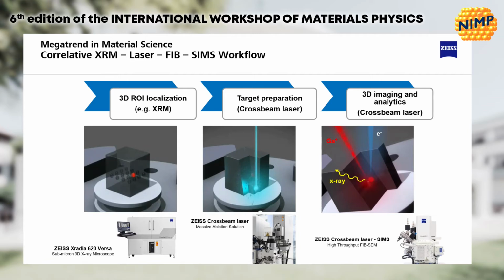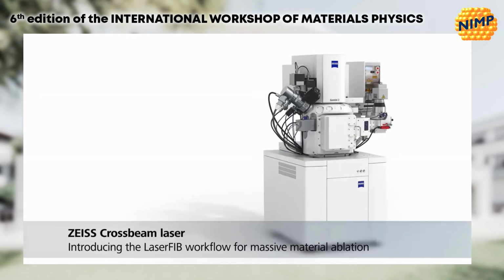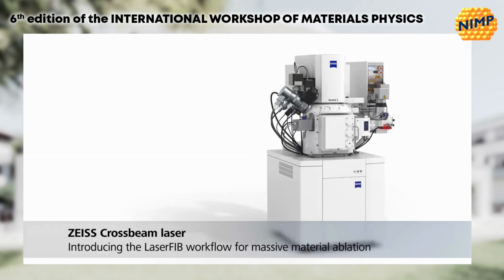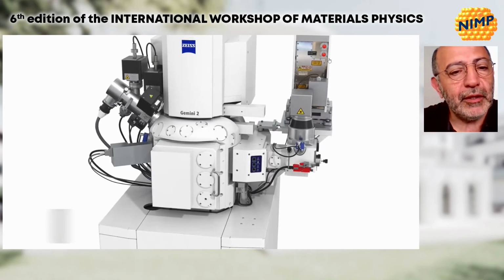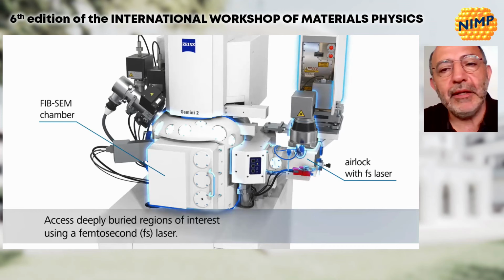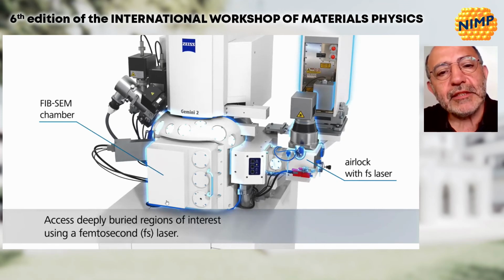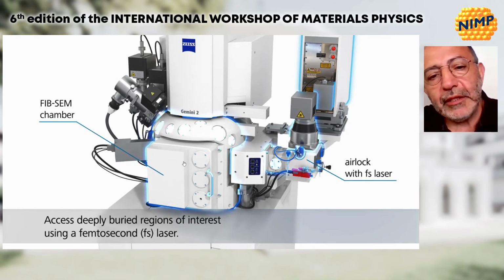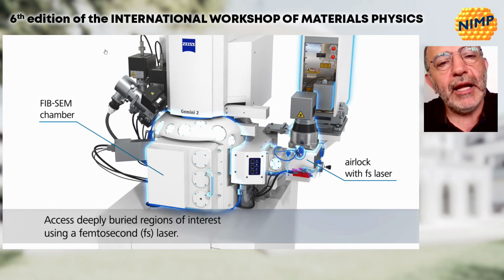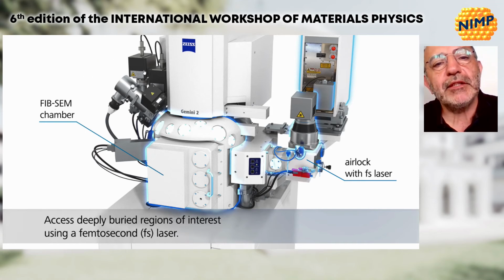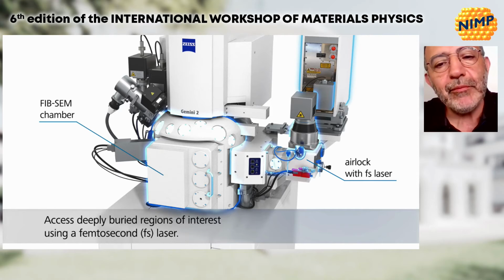And this is the case that I would like to show you. First of all, allow me to show this movie, just to show you what a crossbeam laser FIB is about. What you see here is a standard modern state-of-the-art dual beam or crossbeam system equipped with a field emission electron column. We have a gallium FIB. Behind the gallium FIB is a mass spectrometer, a TOF-SIMS. And on the right side, you see a laser system.